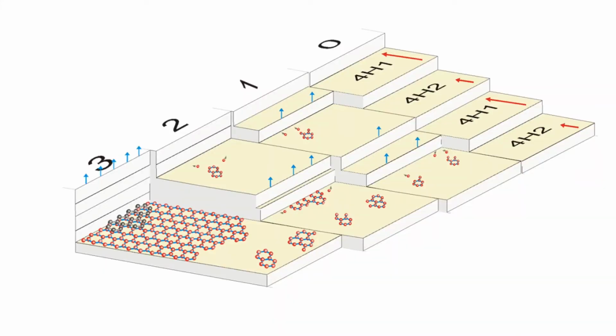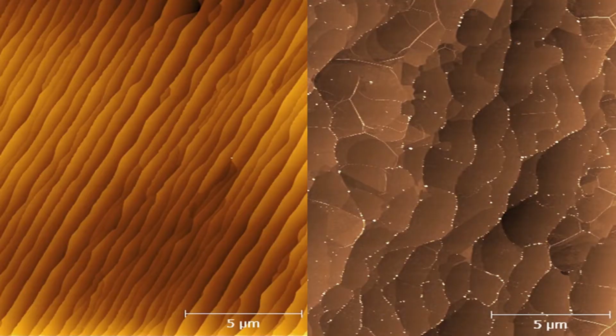And in the case of silicon carbide, depending on the polytype, you have various bilayers, and then there are several small steps which are merging. The surfaces can look very different depending on how we have pre-treated the substrate. Either there are intentionally made steps, or there will be some domains and so on, and different features. In some cases, these are not good for some applications, but sometimes actually these features are useful. For example, on the left side, you have straight steps, and when we have such a surface from the beginning, we can create ribbons of graphene along the steps.